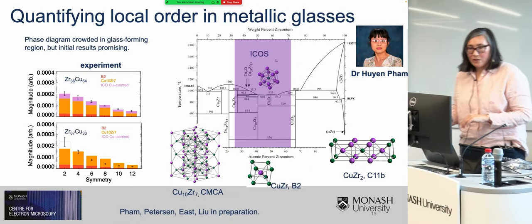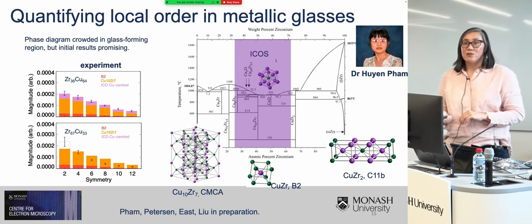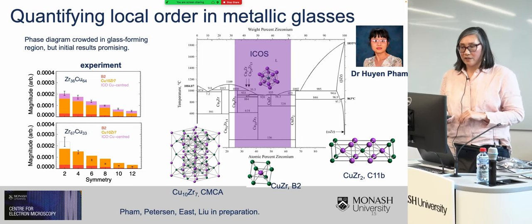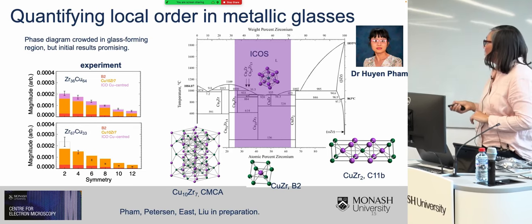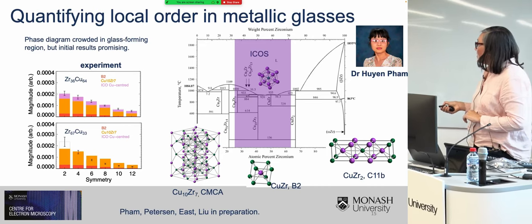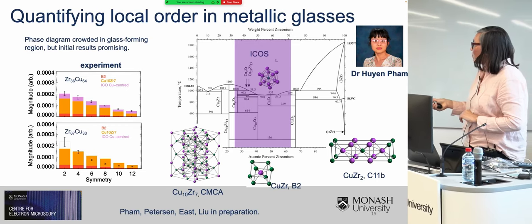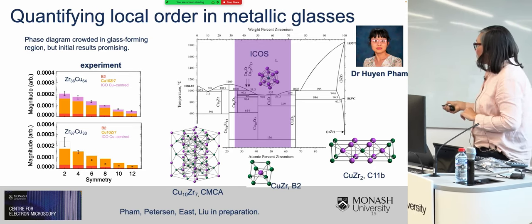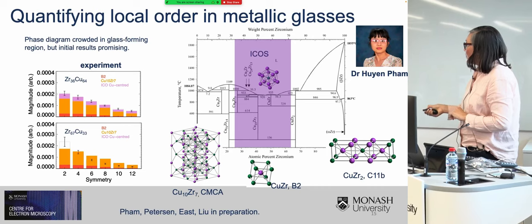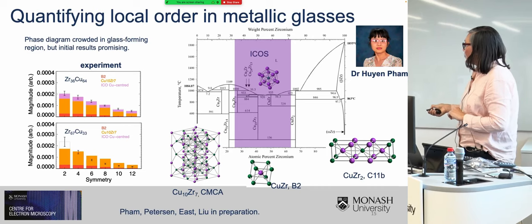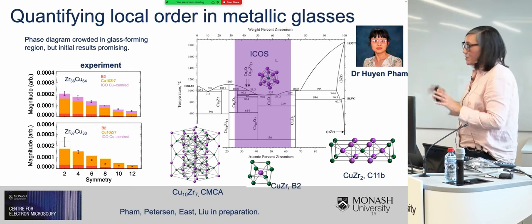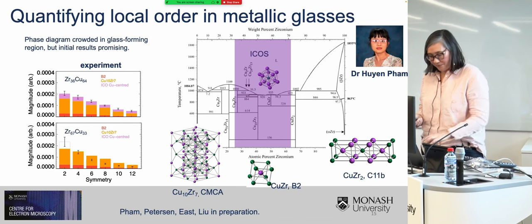So at the moment, I'm on the way to demonstrating the usefulness of this approach for metallic glasses, and Huyen Pham is really helping out with her hard work. So you can see that this is promising in the sense that our average Fourier coefficients seem to be fitted quite nicely, considering the angular symmetries that you expect from the polyhedra, from the crystalline phases in the phase diagram. But we still have a little bit of work to do there.